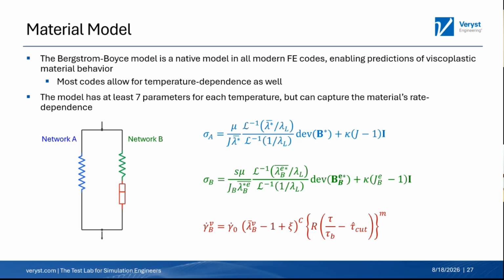So when we calibrate it, we have 7 parameters that we need, and I've shown the structure of the model there over at the left, and I've color-coded it to help us understand what's going on here. So in this model, we have 2 parallel springs shown by the green and the blue squiggles, and we're going to call each one of those legs a network A and a network B. The stress in network A is given by that blue equation, which if you have seen this before, that's the Arruda-Boyce or 8-chain hyperelastic model. So that's a non-linear, completely elastic model. And we can see that there are 3 parameters there. There's a bulk modulus kappa, there's a shear modulus mu, and then there's a lambda L, which is a locking chain stretch.